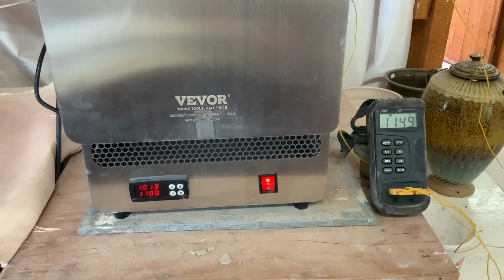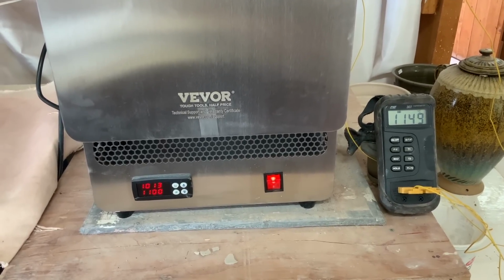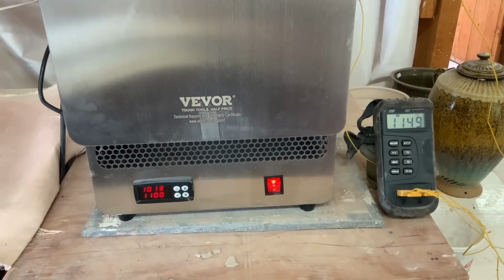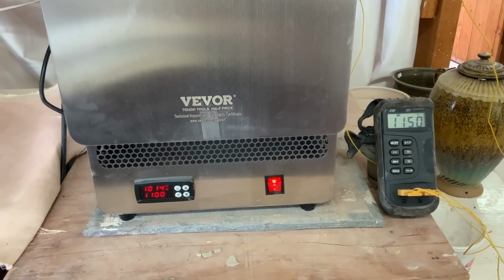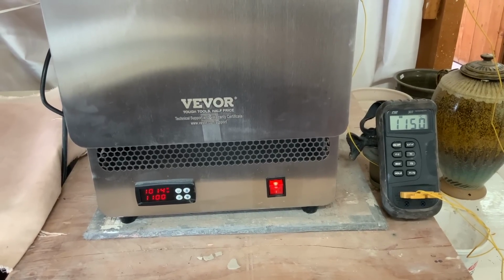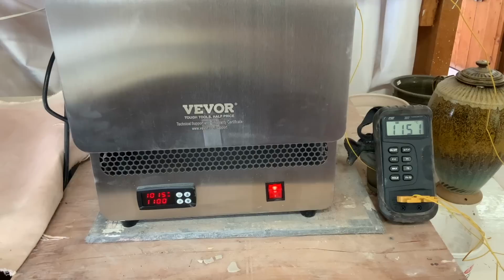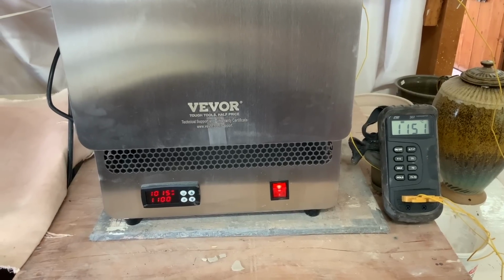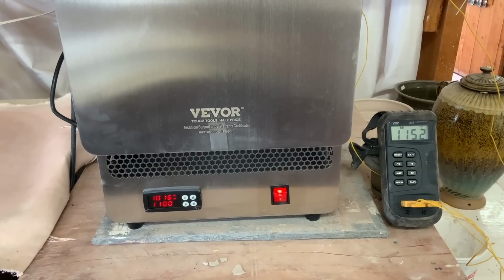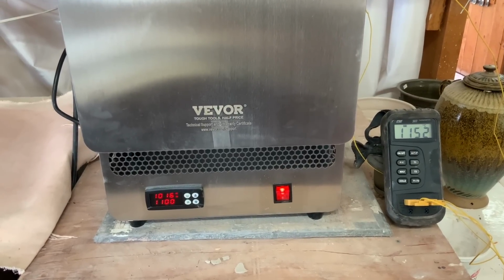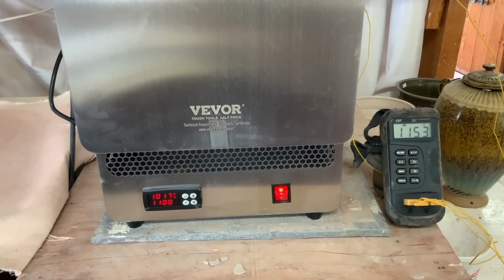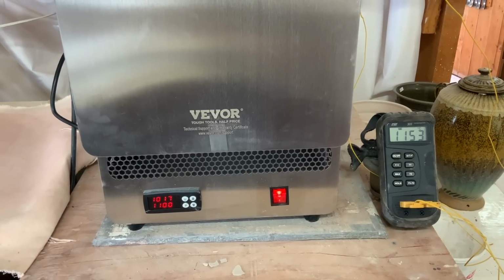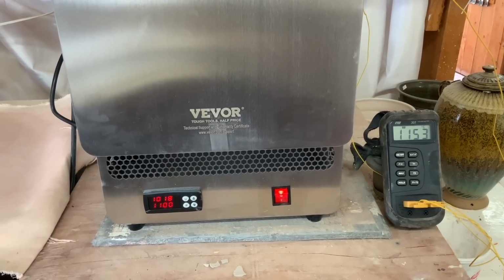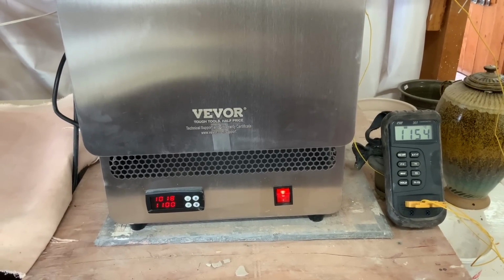But it's crucial that I don't go over 1200, and we've only got 50 degrees to go, so it's not going to even out enough. And that's why I set it at 1100, because if my pyrometer gets to 1200 and theirs has not reached 1100, we will be overfired again. So for the next 10 minutes I have to watch this, because it goes up that fast. You can see it as it's increasing.